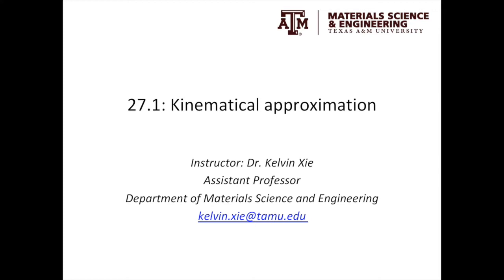I decided to discuss kinematical approximation here for three reasons. First, in the diffraction section of this course, we mainly focused on the dynamical approximation, where the intensity of the diffracted beam and the intensity of the direct beam are dynamically coupled. The dynamical effect arises because the diffracted beam is scattered by the same set of atomic planes multiple times. If the sample is very thin, then we can calculate the intensity of the diffracted beam using the kinematical approximation.